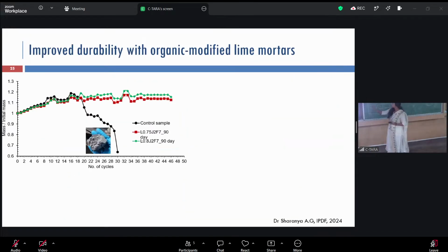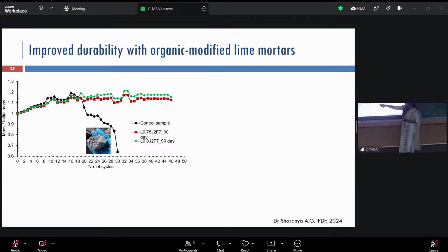At larger scale, what we did was, we made cubes with jaggery and without jaggery lime, and we subjected them to accelerated salt weathering cycles, extreme salt exposure and drying. And here we are measuring the weight loss after every cycle. The black one is the failed sample after 20 cycles, which did not have jaggery, but it was enhanced with pozzolan. But on the top two ones, when we are adding jaggery, it was not failing at all. So it had good salt weathering resistance like the coral limestone.